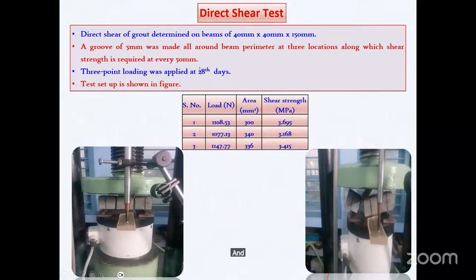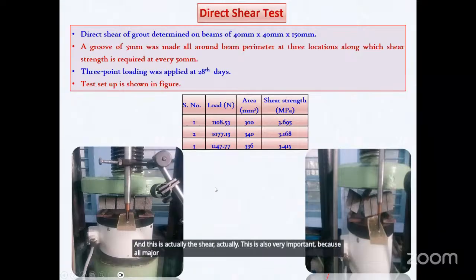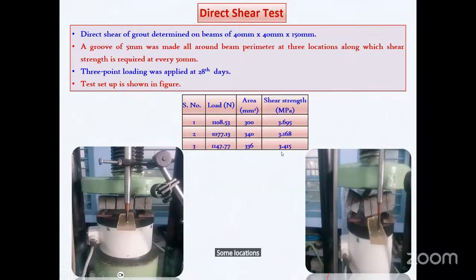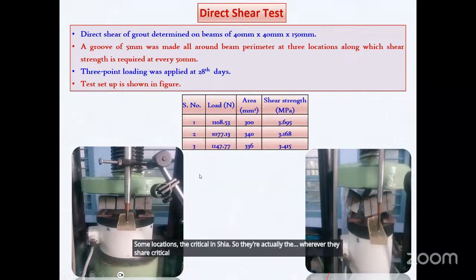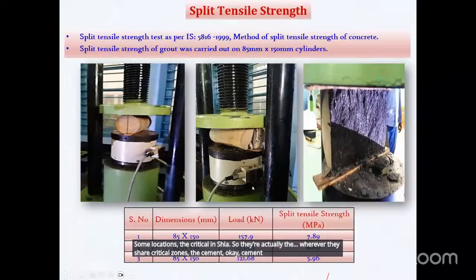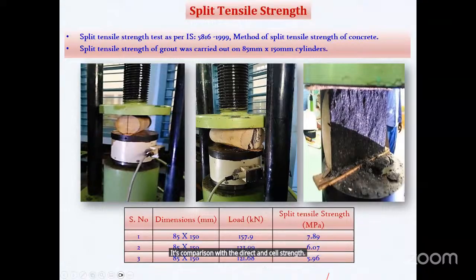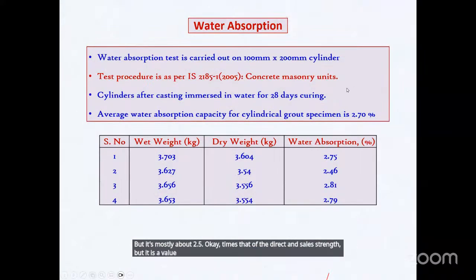And this is the shear strength. This is also very important because in all major constructions, all major structural components, some locations are critical in shear. So wherever there are shear critical zones, the cementitious product can be advantageously utilized. As a routine test, splitting is done to understand its comparison with the direct tensile strength. It is the indirect tensile strength of concrete, mostly about 2.5 times that of the direct tensile strength. But it is a value for the engineers to understand.